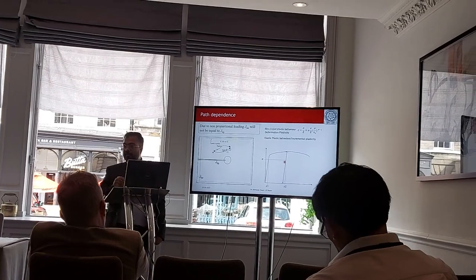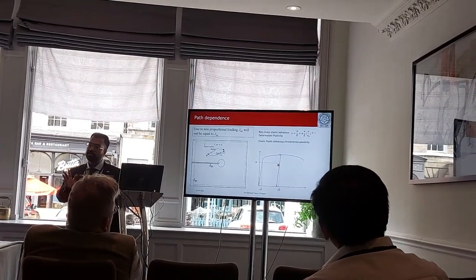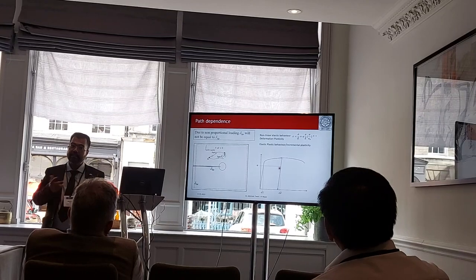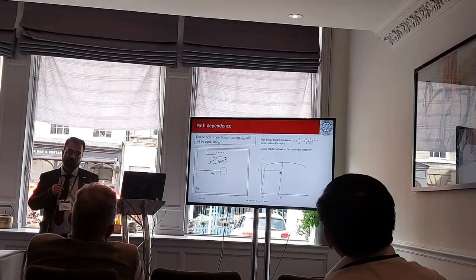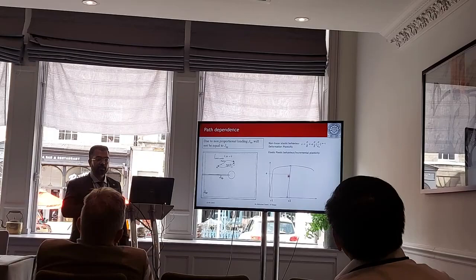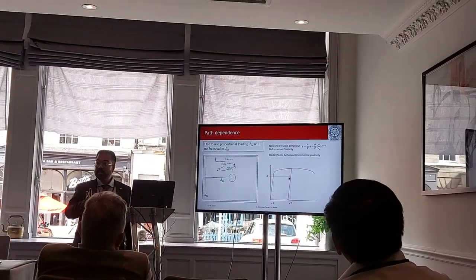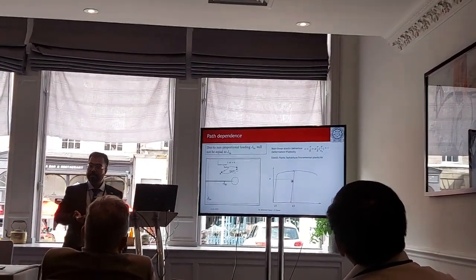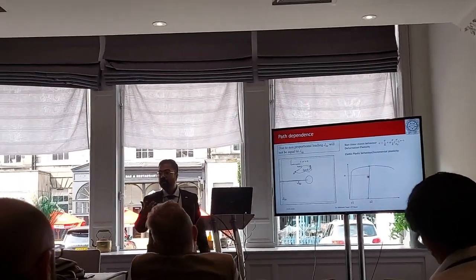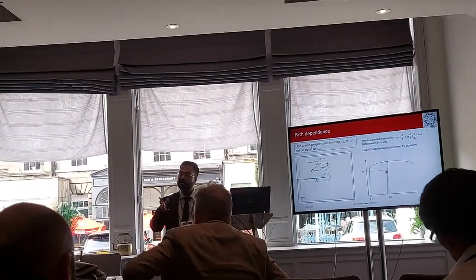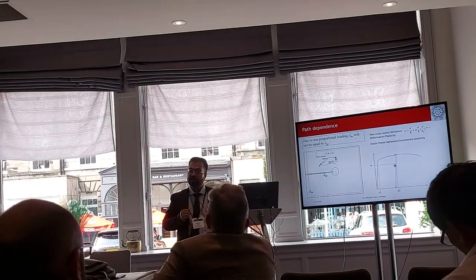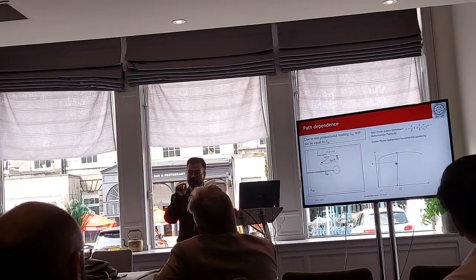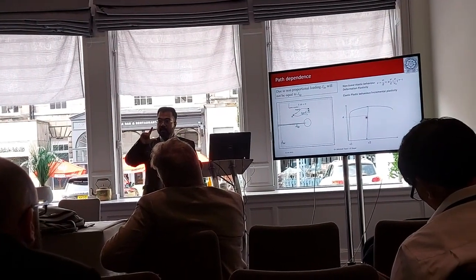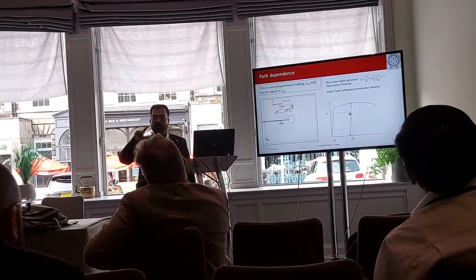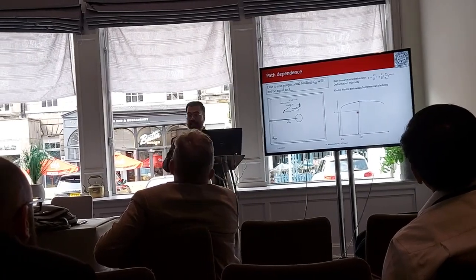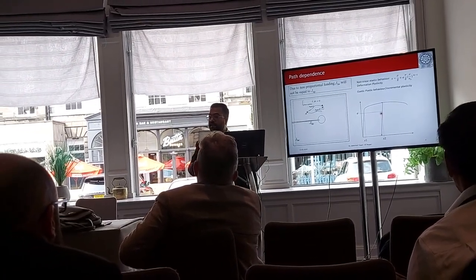The real materials deform in this way. So if you unload, for the same value of stress, you will have two different values of strain. And this is not incorporated in the Ramberg-Osgood equation or deformation plasticity. So you'll have to use incremental plasticity, and then the J integral is not valid. So the J integral is not valid when you have unloading. This is known. Unloading happens as soon as you have crack growth, because the point which was connected in the ligament, as soon as the crack grows, that point has unloaded now. Because of that, you have unloading, you cannot avoid it. Therefore, for any crack growth test, the J integral is theoretically not valid.